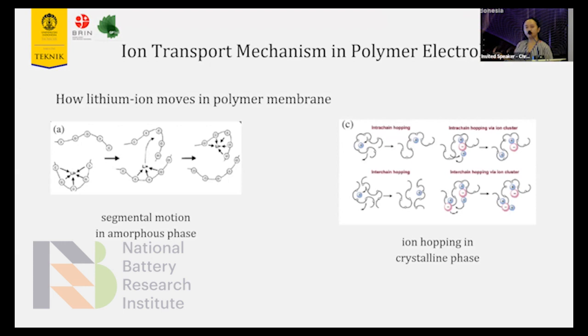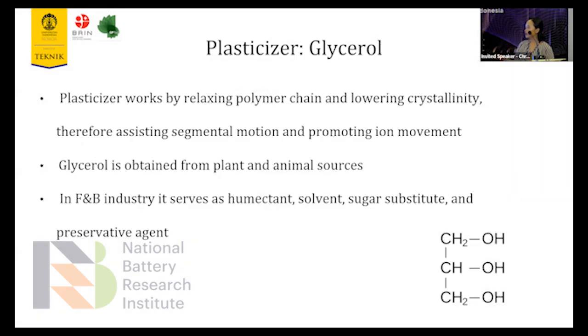This is an overview of ion transport mechanism in polymer electrolyte. A lithium ion moves between amorphous and crystalline segments of the polymer using segmental motion as well as ion hopping. So to make ion mobility easier, we facilitate that using plasticizer, because plasticizer works by relaxing polymer chain and lowering crystallinity, therefore assisting segmental motion and promoting ion movement. And glycerol is green because it can be obtained from plant and animal source.